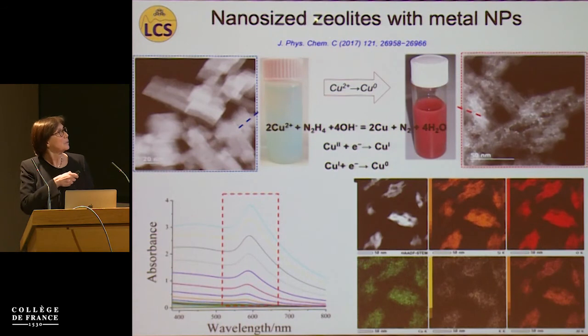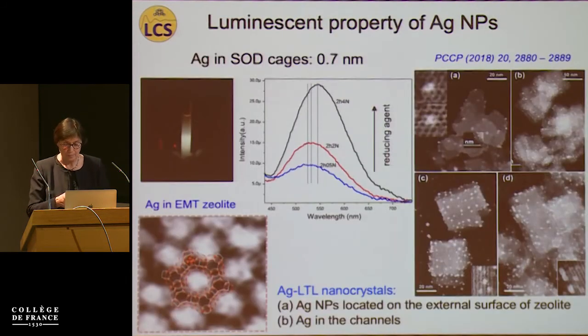The first example is on the nano-sized zeolite with LTL type structure, stabilized in colloidal suspension, containing copper 2+, and under chemical treatment with hydrazine, we have been able to find the conditions where we could stabilize only copper 1+ or copper 0. Also, this process was followed with in situ UV spectroscopy.